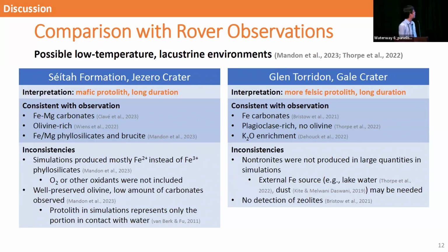Our interpretations are consistent with observations for carbonate compositions, the igneous compositions, and some aspects of the secondary composition. But there were some inconsistencies. For the Séitah Formation, our simulations produce mostly iron 2+ phyllosilicates instead of the iron 3+ phyllosilicates detected by the rover.